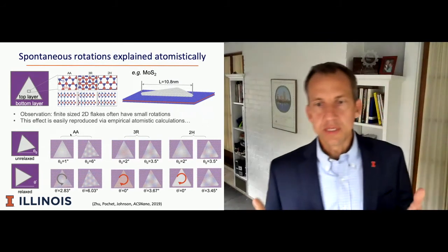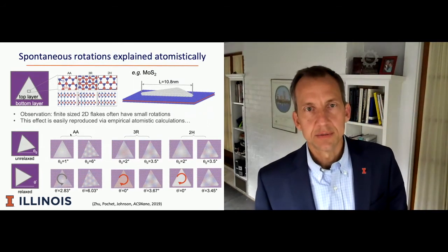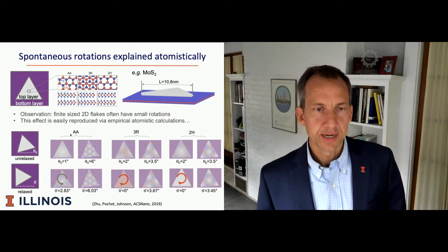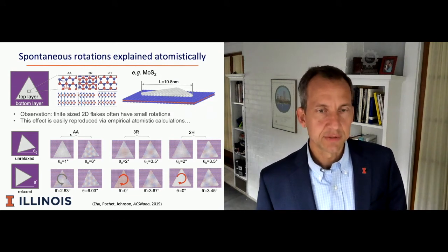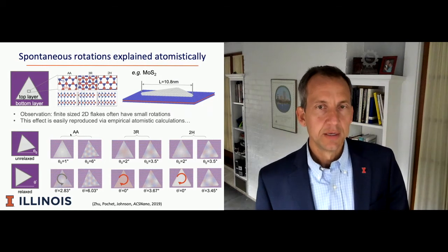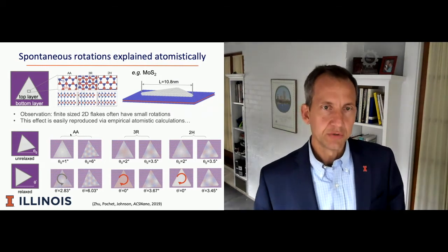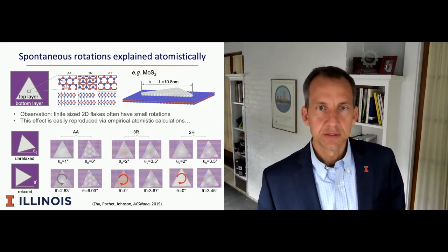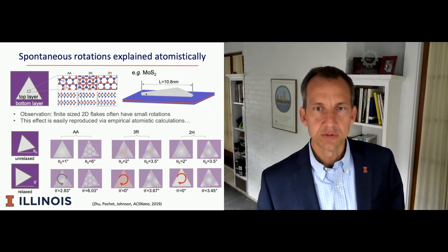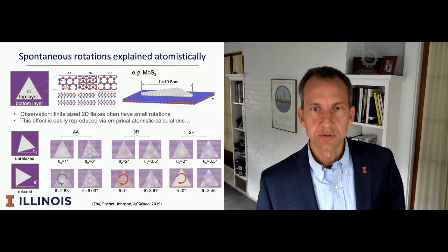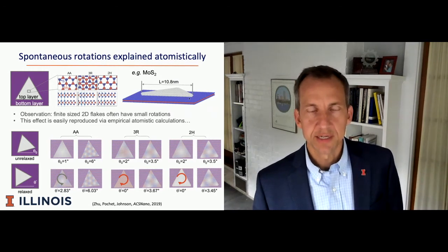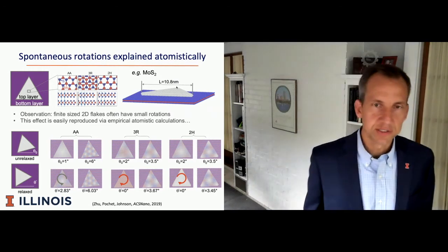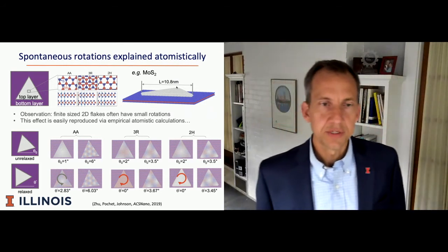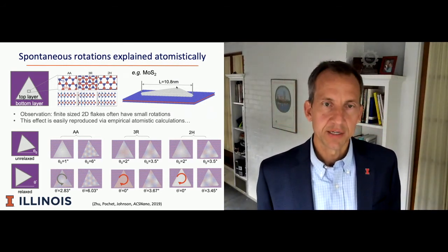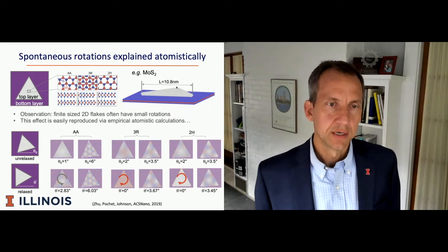So we can observe this using atomistic modeling in molecular dynamics or lattice statics through energy minimization methods, and that's what we're doing here. Again, the top figure shows you the same image I showed on the opening slide. So this is an MoS2 flake on a larger MoS2 substrate. In this case, it's about 10 nanometers. We can look at much larger systems, of course, but the features of this observation tend to be magnified at the smaller sizes. So we start there.